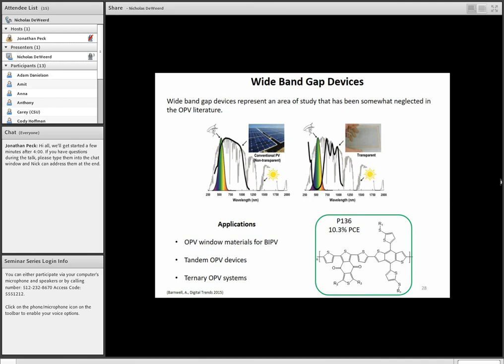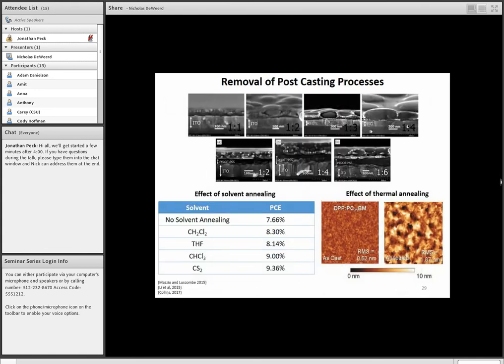This P136 is actually a wide bandgap polymer, and with the correct morphology and acceptor pair, you're able to get 10.3% efficiency from that device. Another technology that I think you could actually consider this kind of moving away from a certain area of research, I hope. But right now, to get the highest efficiency devices, there's usually post-processing that's required for the organic photovoltaic bulk heterojunction. That's either solvent annealing or thermal annealing.